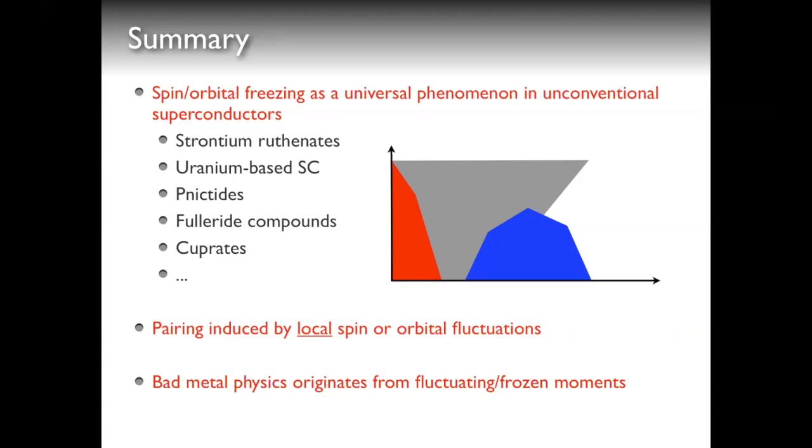There is a very large number of very small mini gaps that are opened due to the distortion of the system, and this in itself already blurs the standard Drude behavior of the optical conductivity. That is a very robust conclusion, which is already there just at the pure DFT LDA level. As a result, I think one should be a little careful, but probably Philipp, you agree with that, about over-interpreting the 1 over square root of omega optical conductivity in the ruthenates. That's all we wanted to point out here.